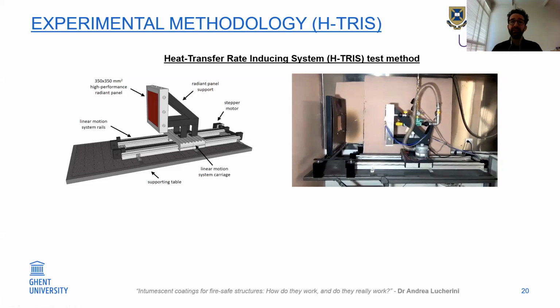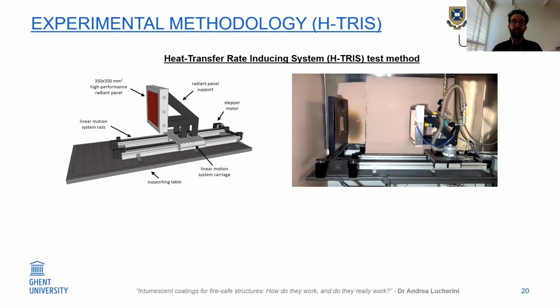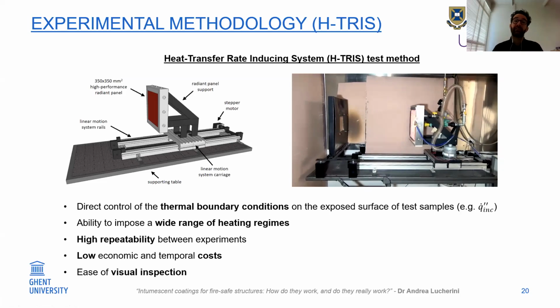This is a novel experimental test in fire safety engineering, and it has several advantages. The first one is that you can have direct control of the thermal boundary conditions on the exposed surface of test samples, for example by controlling the incident heat flux at the surface of the sample. Then it has the ability to impose a wide range of heating regimes by simply moving the radiant panel back and forth, or faster or slower, towards the sample.